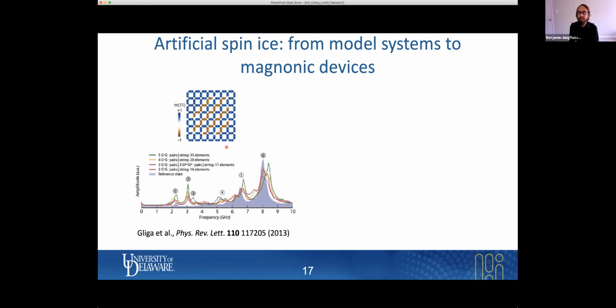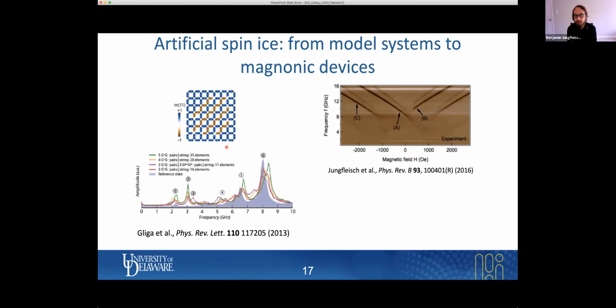So the first thing we did is a very simple experiment. We patterned a square lattice on a microwave antenna and performed ferromagnetic resonance. I'm going to talk about this in more detail in a moment. Here, I just want to show you the highlight. So we see here this rich mode spectrum, a lot of different modes. And in this paper, we found indications of certain spin-ice states present in the system using a simple resonance experiment.